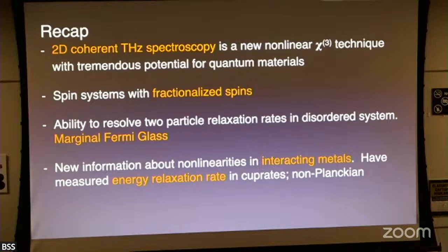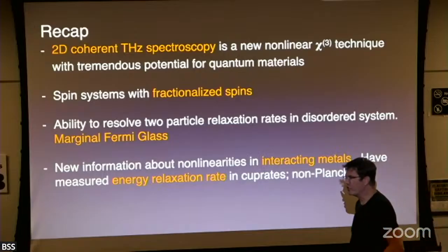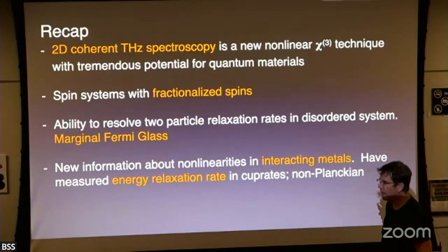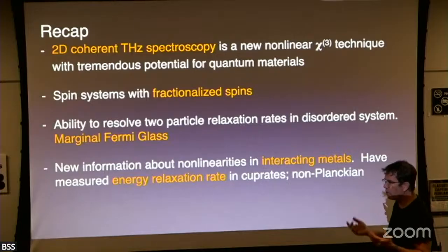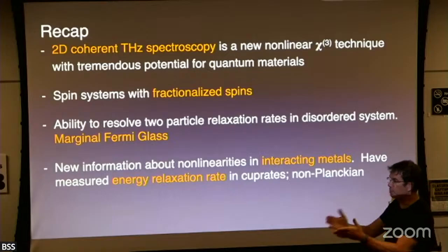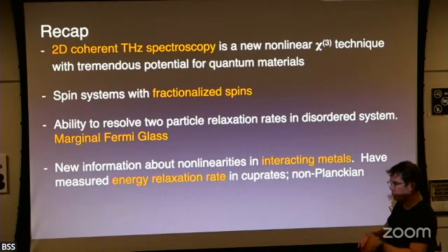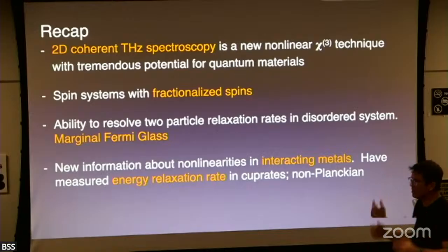So I'm not counting superconducting states. Superconductors are very nonlinear just in general. So I don't have a comparison to what's bigger or smaller, but there are interesting dependencies. But all superconductors are very nonlinear. As you drive a superconductor at large currents, you start to break charge carriers, and that changes the conductivity at finite frequency. And so, whether they're more or less, we've done work on niobium nitride, a conventional superconductor. Cuprates are not any more nonlinear than niobium nitride, about the same, I would say.